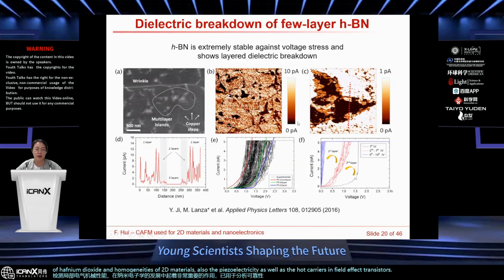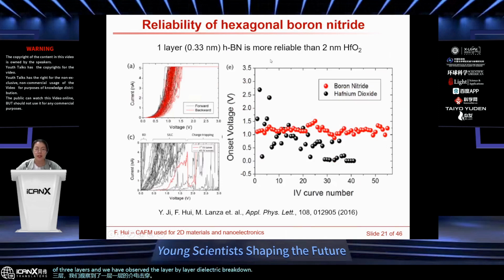During my postgraduate study in our group, our first work was to use C-AFM to analyze the dielectric breakdown of CVD-grown hexagonal boron nitride. In this work, we analyzed boron nitride islands, which consist of 3 layers, and we observed layer by layer dielectric breakdown. Comparing with traditional hafnium oxide, we have seen that hexagonal boron nitride shows more reliable behavior, because it doesn't show obvious reliability problems such as charge trapping or defect trapping,